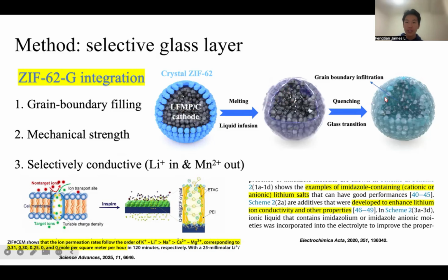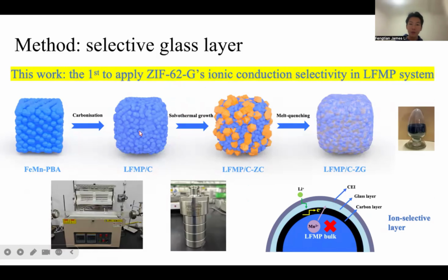So it's in itself boosting conductivity in the first place. Plus, it's stronger because it's amorphous instead of crystalline. Finally, it's selectively conductive. It specifically selects lithium ion as reported in several literatures, and therefore it prevents manganese out. So this is a smart way to only allow lithium ion transport in while repressing all of the manganese dissolving out. So ensure both conductivity and structural stability. Here's a scheme diagram for synthesis. Here's a better demonstration if you are confused by the previous explanation.